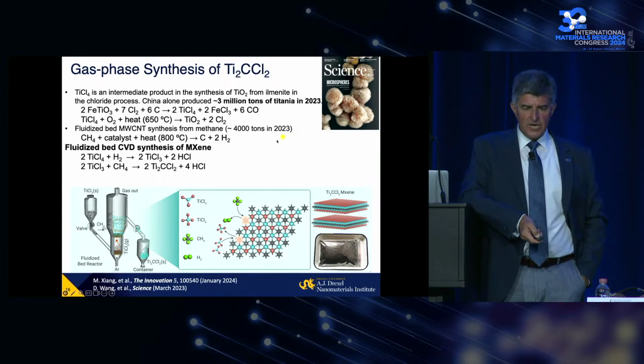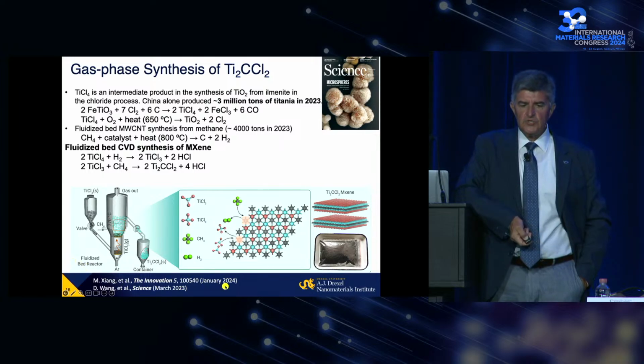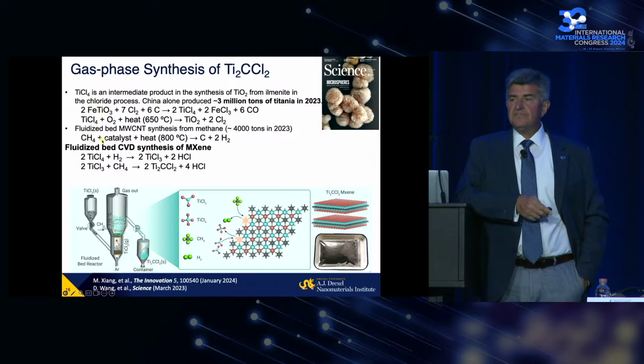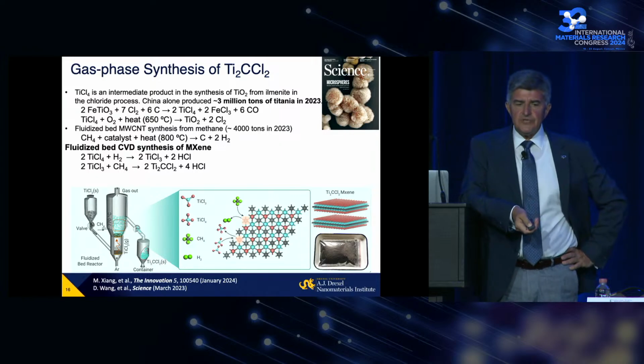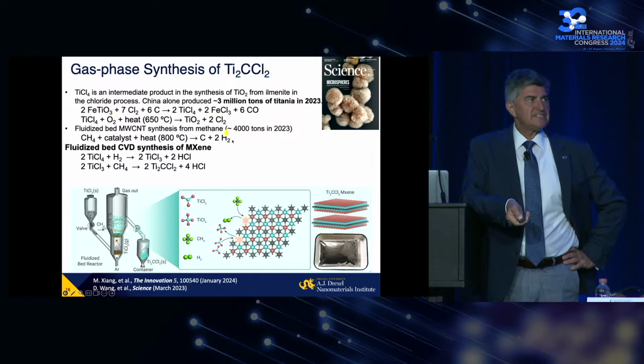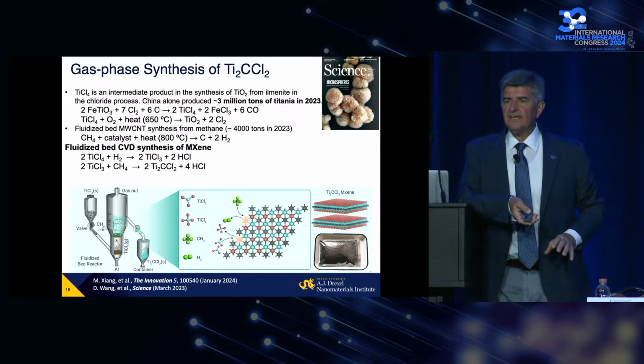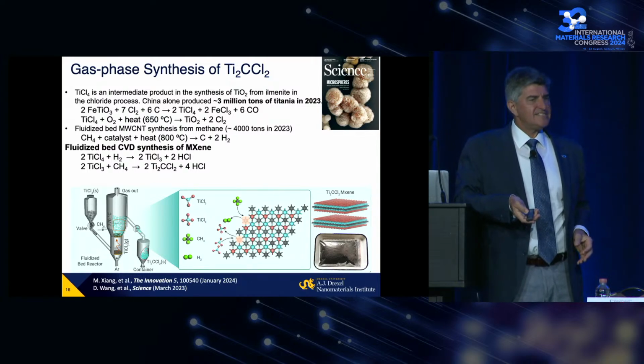But a group from the Chinese Academy of Sciences, with one of my former students involved, published this paper in January this year on fluidized bed synthesis of MXene from titanium chlorides and methane. Titanium tetrachloride is an intermediate material for synthesis from ilmenite to titanium dioxide. If you look at the white ceiling, white walls in the back, it's all titanium dioxide. You probably all use sunscreen with titanium dioxide. 3 million tons of titania were produced in China just last year.